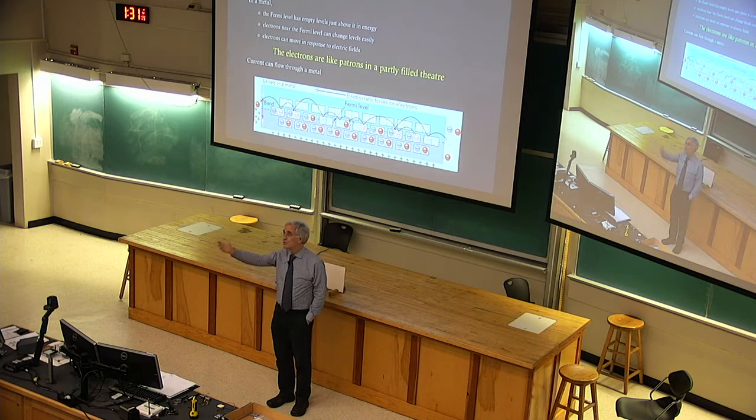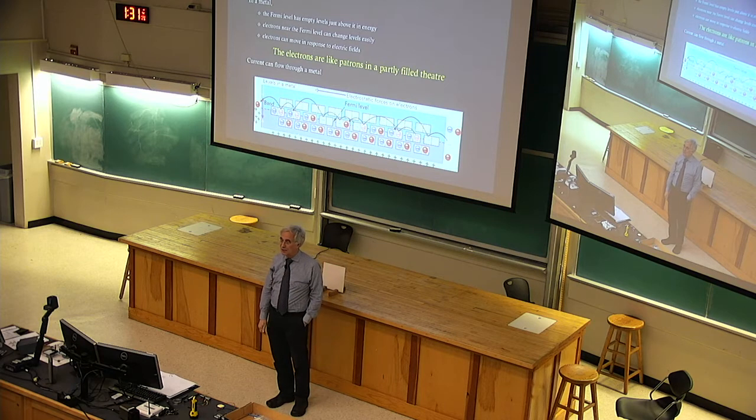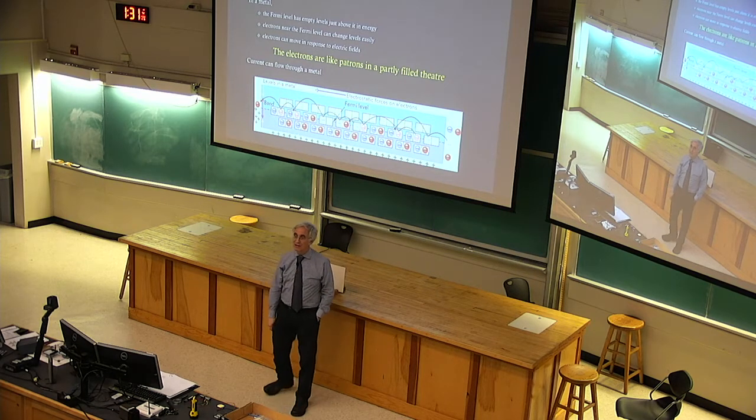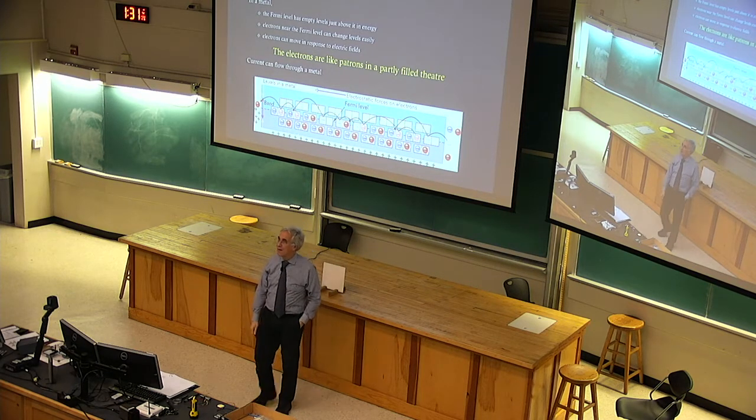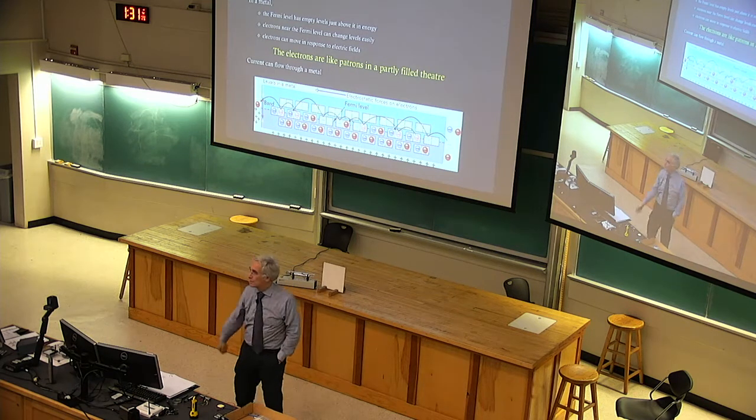So all the metals that you've encountered fit this bill. The electrons, as they're going in there, when they finally fill, you run out of electrons, they have partially filled bands. And it is energetically very easy for the electrons to shift into new standing waves and therefore make progress across the material.